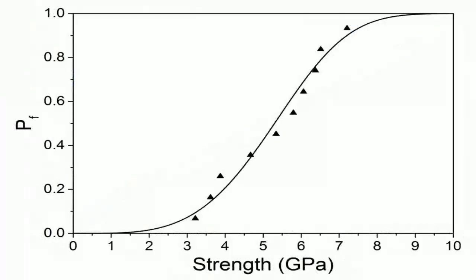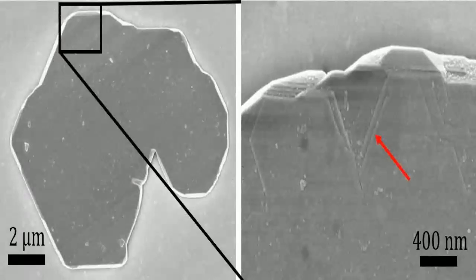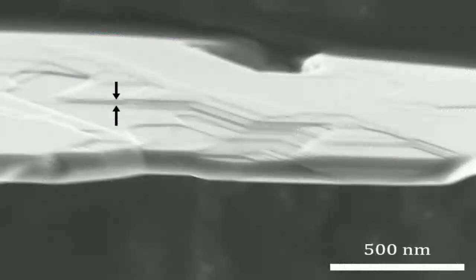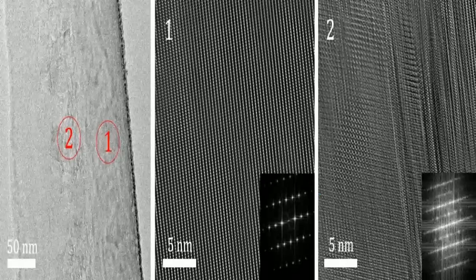And they saw this R-curve behavior. They did, and showed how different platelet orientations, testing cracks growing across filaments versus between filaments, led to different R-curve behaviors. They even printed and tested a structure inspired by nature, mimicking the tough, layered, rotating structure found in things like the mantis shrimp's punching club, called a bouligand structure, and showed it gave good toughness too. That's incredible, using robocasting to create these complex bio-inspired structures specifically to enhance toughness.